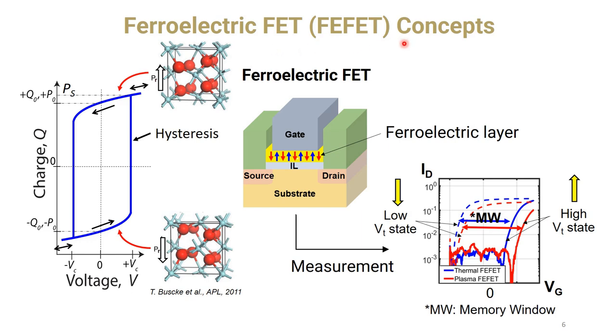The FeFET concept is very simple. Depending on the position of the oxygen atom in HfO2, we are currently commonly using HfO2 as a ferroelectric layer, and when the oxygen atom is at the bottom, it is polarization up, and when the oxygen atom is at the top, it is polarization down. So depending on the oxygen atom position, we have different states, polarization up and polarization down.